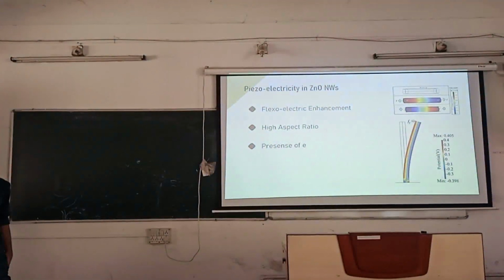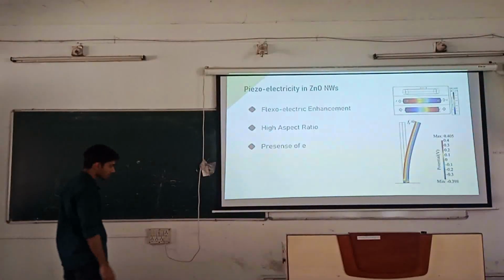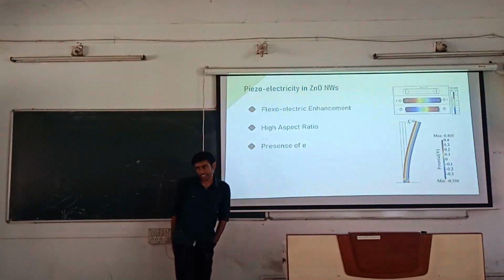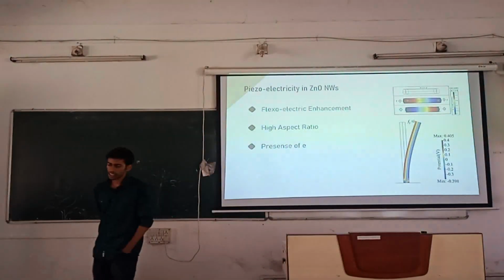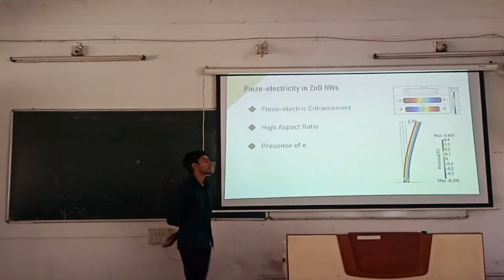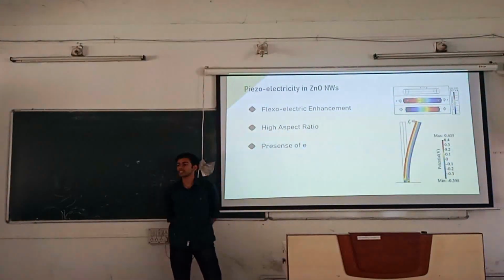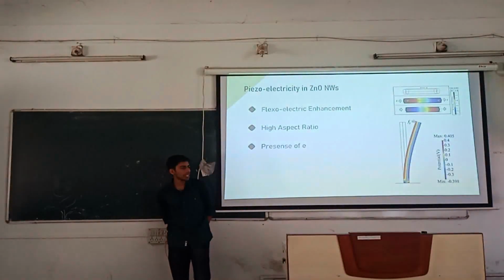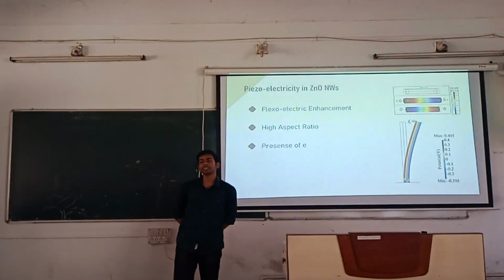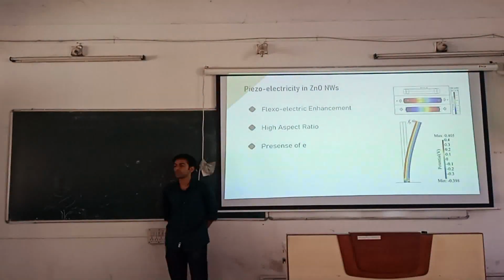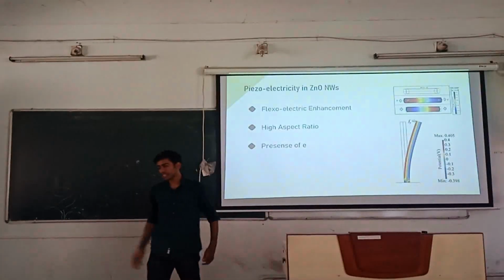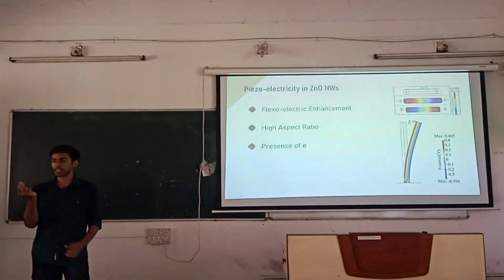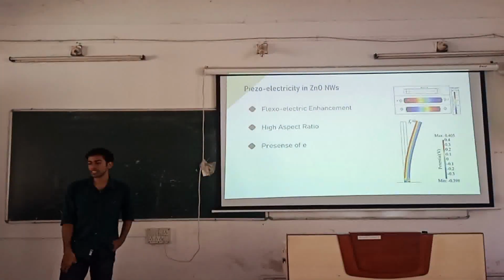And because of the high aspect ratio, that is the high length to breadth ratio, there was a theoretical analysis of zinc oxide crystal done. In that it was shown that the piezoelectric output voltage is inversely proportional to the breadth of the nanowire and independent of the length of the nanowire. This inverse proportionality to breadth is very important because we are dealing with 50 nanometers, so we will be getting a very high amount of voltage. So that is one advantage of nanowires.